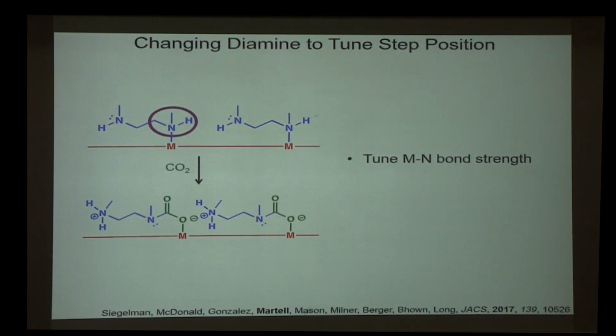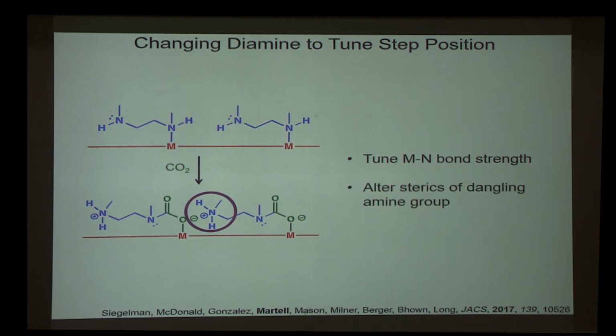The specific changes we wanted to make were the following. First, you could think about introducing a bulky group on this metal-bound amine. If we do this, it should weaken the metal-amine bond, thus destabilizing the starting material of this reaction. This should make CO2 capture easier to occur. Alternatively, we could introduce a bulky group on this dangling ammonium. This should destabilize the product of the reaction, which is chains of ammonium carbamate. And this should make it more difficult for CO2 capture to occur. So these two changes to the diamine structure should have opposite impacts on the thermodynamics of CO2 capture.